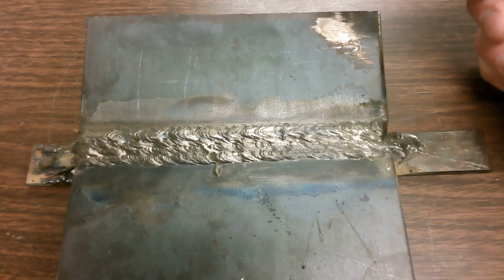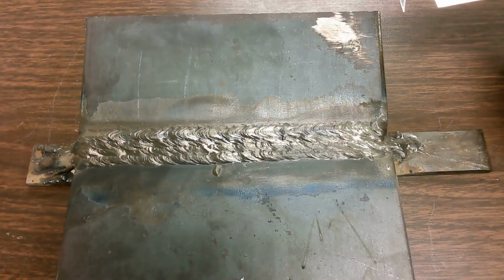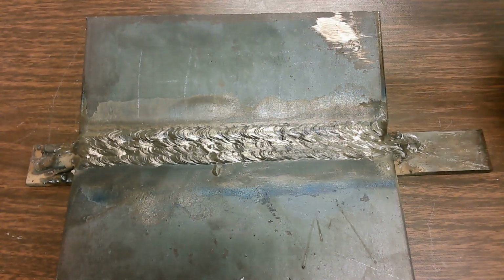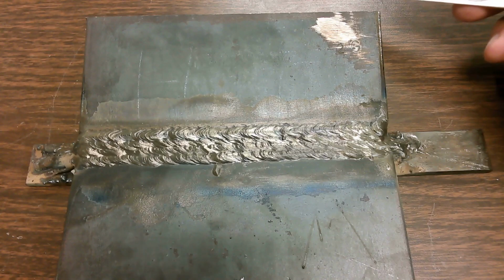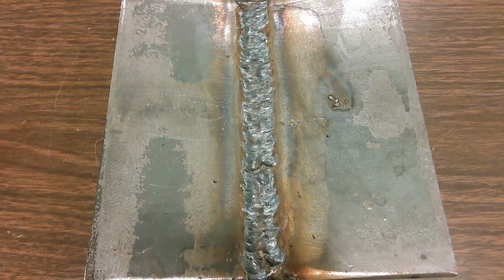It does meet the acceptable criteria for the 2G bend test according to the SENSE standards. Again, it really depends on which standard you're measuring to. If you're going to go to D1.1, again, it's very similar to the SENSE program. They use D1.1 as a reference. But if you're welding to certain other standards, it might not allow any undercut. So you kind of have to look at that and pick a standard. You can develop your own in-house standards as well, but do set that standard. Know what the standard is prior to inspecting. Make sure that the students know and understand that.